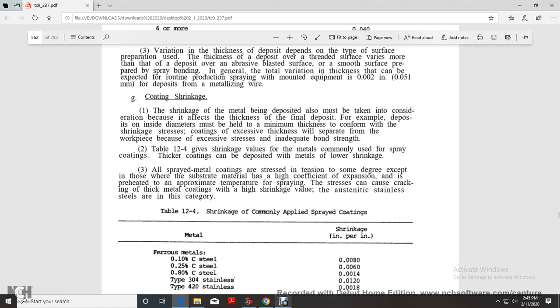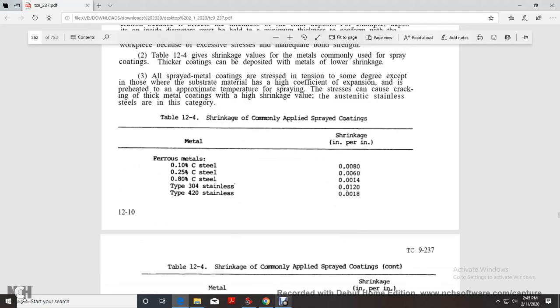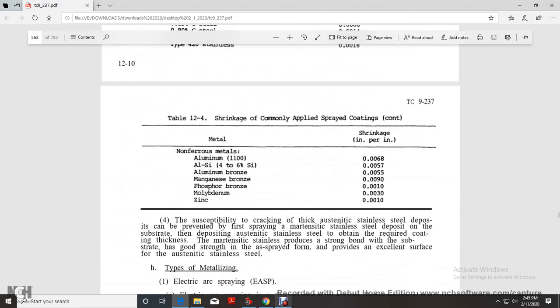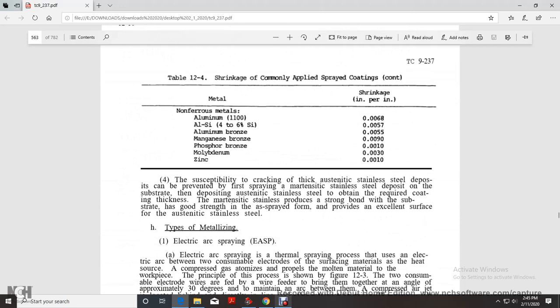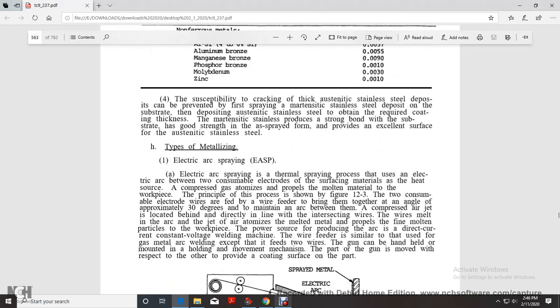All sprayed metal coating is stressed in tension to some degree, except on substrate material with a high coefficient of expansion that is preheated to the approximate temperature for spraying. The stress can cause cracking of thick metal coatings with a high shrinkage value, with austenitic stainless steels as the category. The susceptibility to cracking of thick austenitic stainless steel can be prevented by first spraying a martensitic stainless steel deposit on the substrate, then depositing austenitic stainless steel to obtain the required coating thickness. The martensitic stainless steel produces a stronger bond with the substrate with good strength as sprayed, and provides an excellent surface for the austenitic stainless steel.